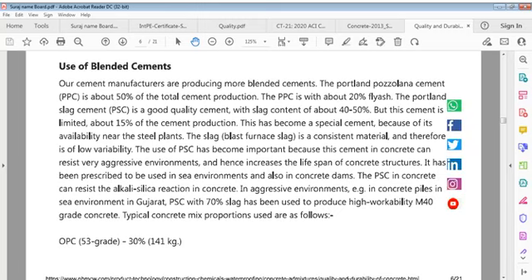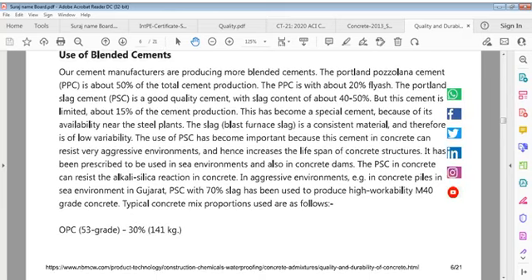Use of PSC has become important because this cement in concrete can resist very aggressive environment and hence increases lifespan of concrete structures. It has been prescribed to be used in sea environments and also in concrete dams. PSC in concrete can resist alkali-silica reaction in concrete. In aggressive environments, namely in concrete piles, in sea environment, in Gujarat, PSC with 70% slag has been used to produce high workability M40 grade concrete.